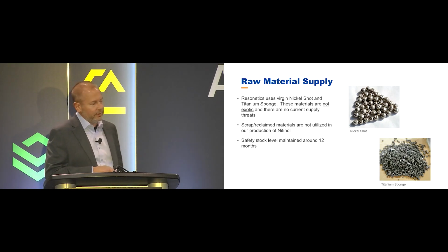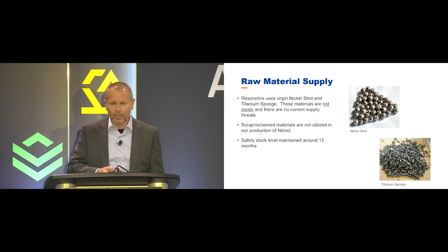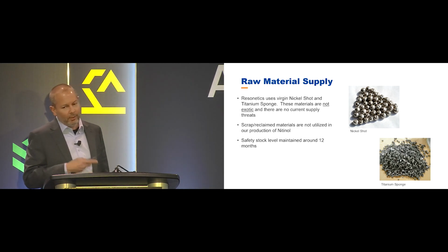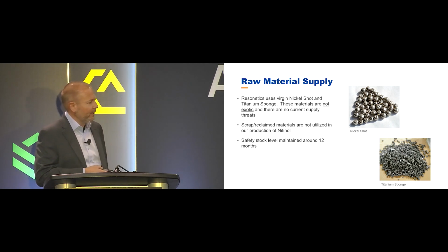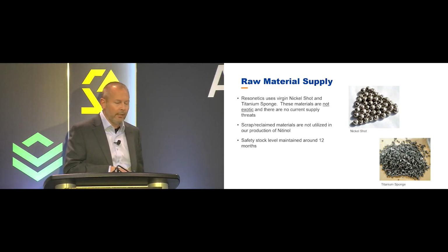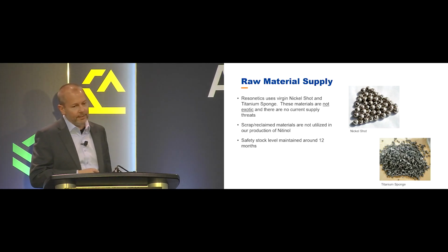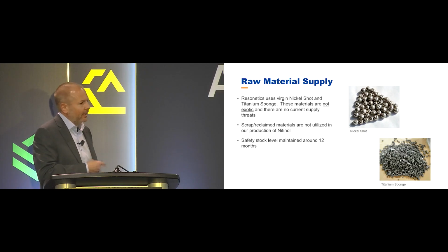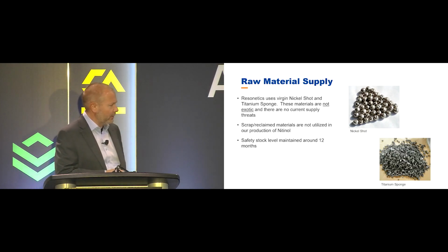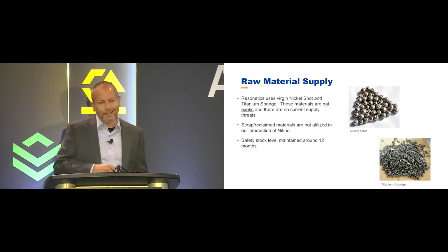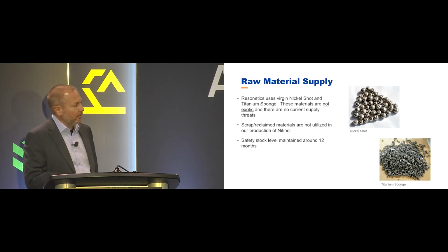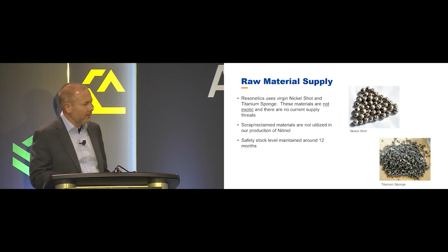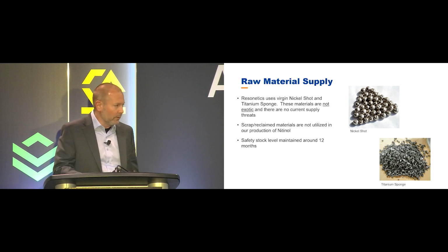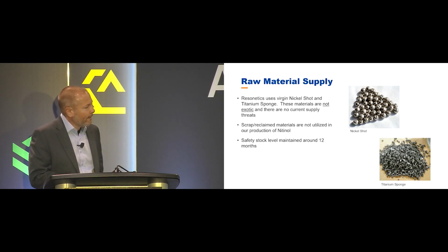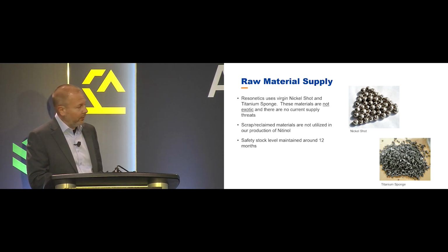We do not use revert, which is remelted material, so anything that we have to scrap through the process, if we downstream we condition, we peel the billets, we get a lot of turnings, or we have crops from the ends. We don't remelt that because every time we melt in a graphite crucible, we pick up carbon. Carbon is an impurity in the material, so all we would do is keep adding carbon to it. So we don't reuse any scrap. I'd like to point out these materials are not exotic. There are some melters using some really exotic, expensive materials, and we're not doing that. These are commercially available materials. We source them from long-term suppliers, and there's really no concern with getting these materials.